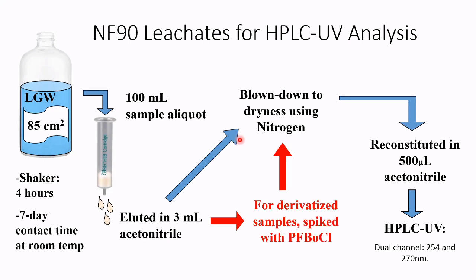So a little bit about our methods. We took a membrane coupon and we just reacted it in a static cell, or a static sample bottle, with lab grade water. We kept it on a shaker for 4 hours. And we left it there for 7 days at room temperature to see if anything comes off of those membranes and if we can capture it in that lab grade water. Then we run it through that Oasis HLB, the SPE that I was mentioning earlier, the kind of broad screen capture, and hope that our analytes are captured and retained on this cartridge.